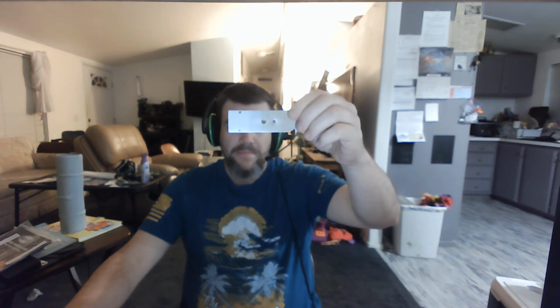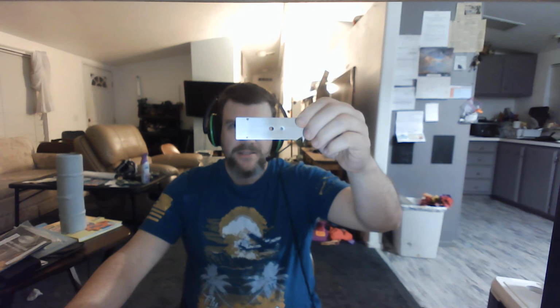One of those things. Okay, you see those two little holes right there. The bottom one is 1/8 inch pore. No, I mean, that's a 16th inch pore. The glare got me. And the top one is 1/8 of an inch. Now, we take our 16th, and we see that pore is too big. Go over the 1/8 inch, and if you go to the very bottom, you have to scroll up a little bit, it's closer to a 3/32, so it is rejected. And the answer explanation is on page 5422.